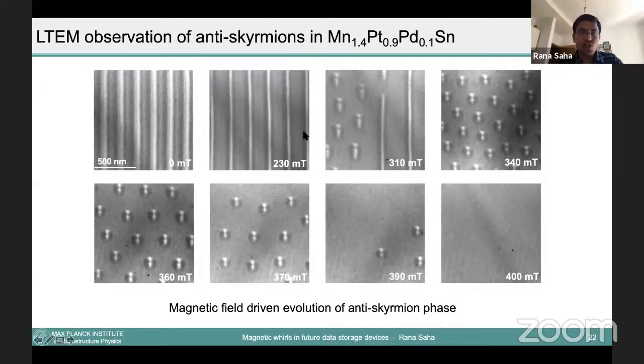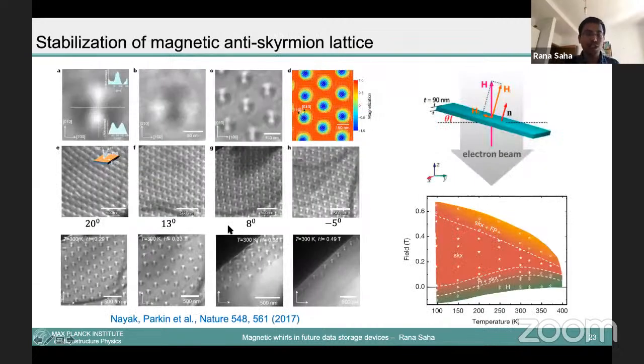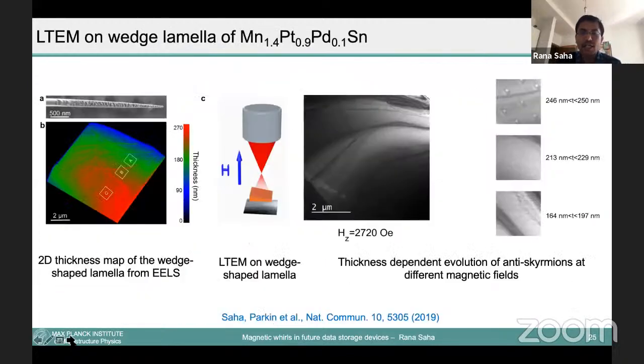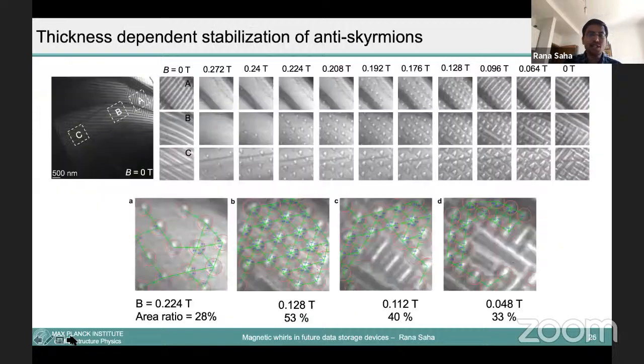So this structure is also stabilized in the microscope using some special kind of arrangement. You can see this is the real structure, and this forms a lattice of these magnetic anti-skyrmions, and when you apply a magnetic field, they vanish into the ferromagnetic state. Even in the ferromagnetic state, they still survive because of some special topological protection. And we can study this as a function of thickness. These are three different thicknesses of the sample. We have a different degree of variation of the stability of these spin textures. And then we studied these different magnetic anti-skyrmions, which have different stability.